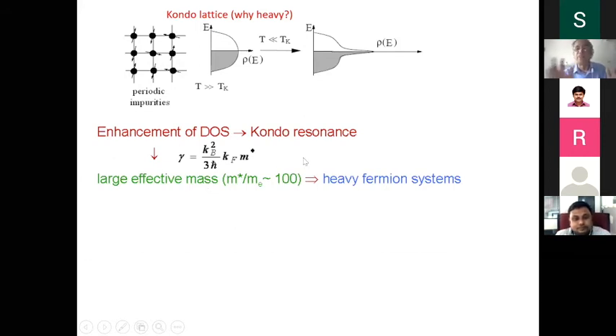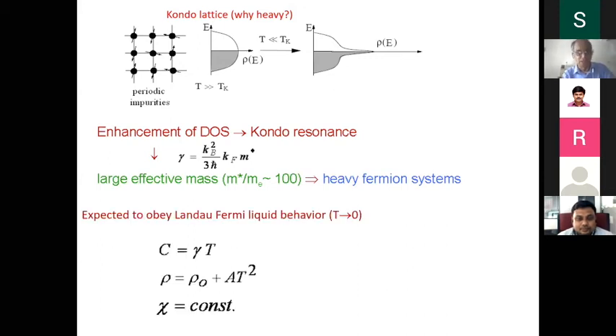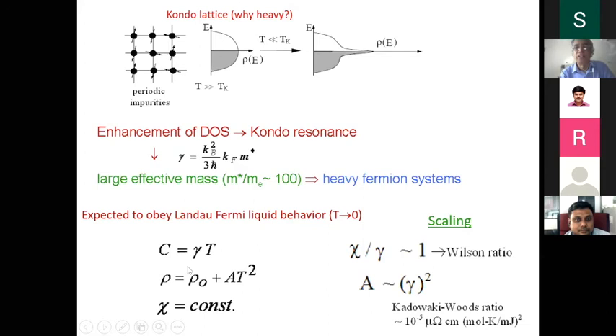They are called Kondo lattices because of the Kondo ion at every site. They are called heavy fermions because the effective mass has gone up because of enhancement of the density of states. These are already established terminologies. They also exhibit Fermi liquid behavior, they behave like any other metal, with gamma T, except this term is enhanced. A, gamma, and chi are enhanced at low temperature. They scale with each other. This is called Fermi liquid behavior. The scaling of these terms is called Fermi liquid.